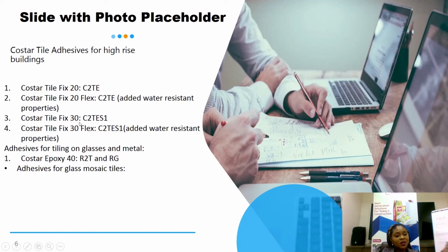Now remember we said that for C2 it's greater than or equal to 1 Newton per millimeter square. It doesn't mean that it's 1 Newton per millimeter square, because the Tile Fix 30 actually has increased tensile strength than the 20, and the 20 has increased tensile strength than the 1 Newton per millimeter square. It's just the standard that it meets. So for the Costar Tile Fix 30 Flex, it's not just the fact that it has added water resistant properties. It comes in two components.